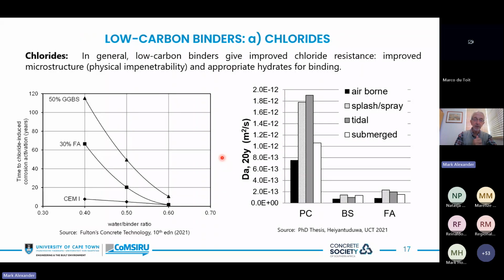Now, looking at some local data, the first diagram on the left there is in fact from Fulton's 10th edition. And I think this was about a 40 millimeter cover, but we've got time to chloride-induced corrosion with a series of binders. First of all, a CEM1, plain cement, a fly ash at 30% and a slag at, say, 50%, and the water binder ratios. And you can see quite clearly here that with the plain Portlands, the plain cements, this says maybe 10 years of corrosion-free life. Well, there's going to be a lot of variability here, but you can see that it's really quite low.